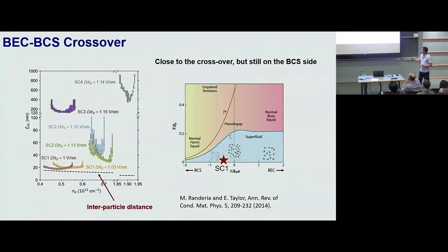And you probably notice that this SC1, SC2 persist with very high out-of-plane magnetic field. Okay, you can estimate the coherence length using that critical magnetic field, and you can compare that to the interparticle distance, which you extract from just the charge density. You find that SC1 is actually pretty close in terms of coherence length and the interparticle distance, and you can put it on this BCS-BEC crossover map: you're close to the crossover, but you're still on the BCS side. Okay, there's some strong coupling, but not very strong.